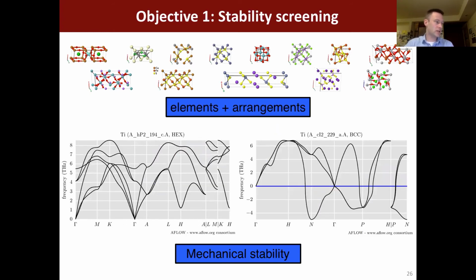So here, for example, we have two different structures, two different polymorphs of titanium. On the left, we have the hexagonal polymorph, which is the one that's stable at low temperature. And you can see here we have this regular phonon dispersion with no negative frequencies. On the right, though, we have the BCC structure, which is the high temperature structure. And you can see at zero temperature, you have these instabilities, where you have these negative frequencies.